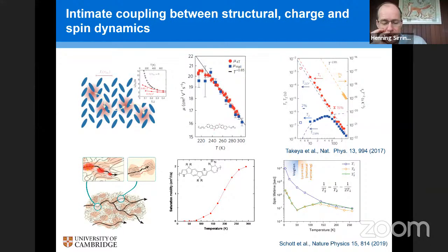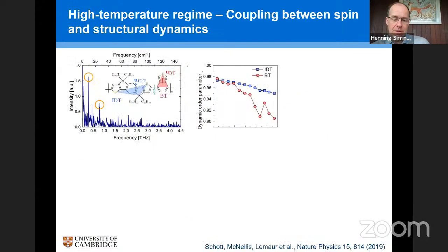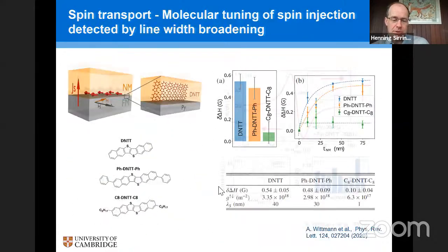That's a little bit complicated because it's probably quite anisotropic. In Angela's measurement, we're measuring the spin diffusion into the film. So typically these organic molecules are oriented with their long axis parallel to the normal of the substrate. And so in the spin pumping geometry, you have spin diffusion essentially across the layers, which is the low mobility direction. Whereas in ESR, what we're probably probing is the spin diffusion in the plane, from molecule to molecule. So it's not directly comparable. Okay, that makes sense. Thanks.